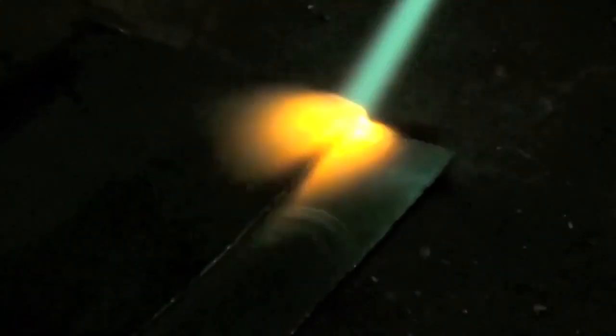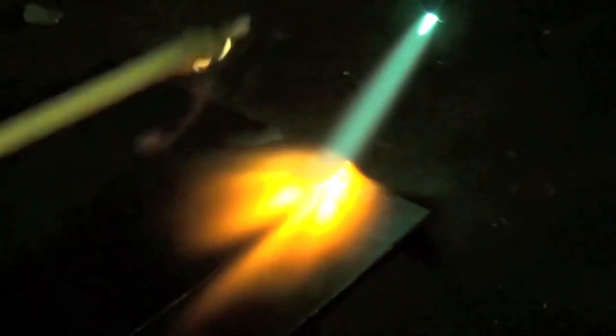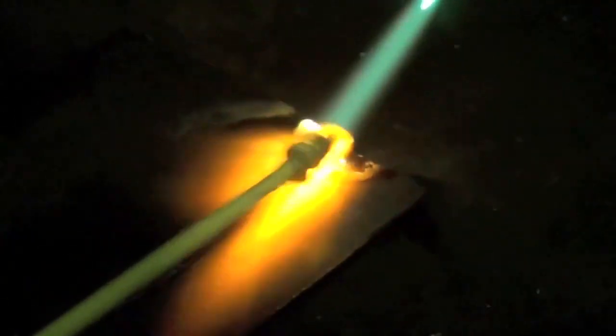It's kind of hard to really see what's going on because you got that flux that's melting. Now when you start to hear that sizzle, that's a good sign that you're too hot and you need to back off for a second because what that is, you're actually burning the filler. You can control your heat input to an extent with just how far away you keep that flame. You're just going to kind of dab, keep it nice and cool. This isn't the easiest thing in the world to see. It's kind of like when you're stick welding with 7014 or 7024—you're going to put out a very heavy liquid slag coating. It looks like I'm getting a lot flowing to the top. This isn't going to give you a nice stack of dimes look like you would with TIG. This one's starting to look pretty messy. I think I got a little too warm.